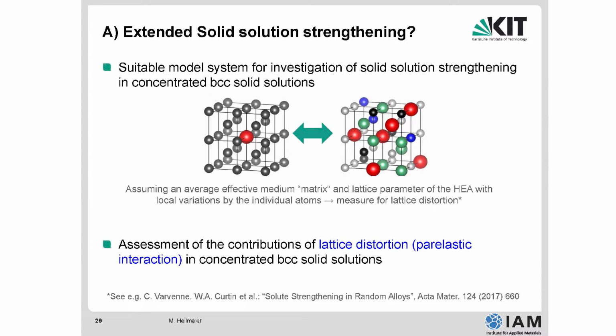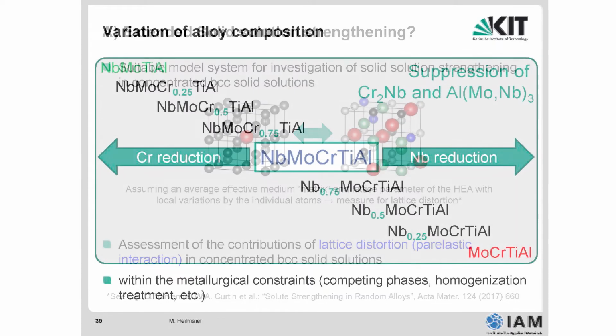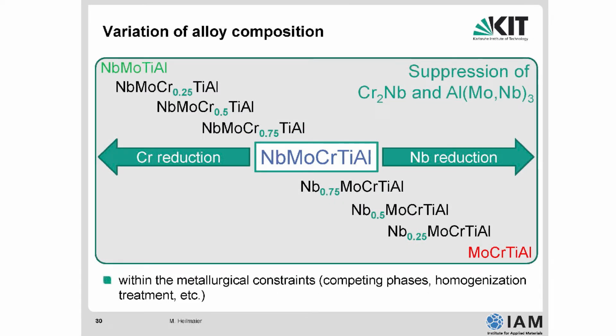What about the extended solid solution strengthening? Where does it come from? It comes from the fact that we mix on a random scale different atoms with different atomic sizes, and thereby we distort the lattice quite a bit. So lattice distortion is what counts in these concentrated systems, either BCC or FCC. And of course you have to measure the lattice distortion appropriately for predicting the solid solution strengthening. That's why we followed an experimental approach. We started from this model system, a 5-component system, and then we varied deliberately either the niobium content, so we took out niobium and ended up at the quaternary molybdenum, chromium, titanium, aluminum alloy, and on the other side we took out the chromium because we wanted to suppress this phase here. The chromium-niobium phase is a Laves phase which is brittle and which deteriorates the chemical composition.